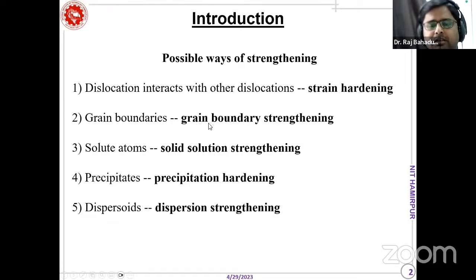Grain boundary strengthening is nothing but increasing the length of the grain boundary in the material, or you can say reducing the grain size of that material. Both are the same thing, and we can create more and more hindrance in the path of dislocation. If the grain size is coarser, then dislocations move easily. If the grain size is fine, then the path for movement of dislocation is less. The moving dislocation will find obstruction, which acts as a hindrance, and therefore strengthening takes place because we have to apply more and more load to deform the material.